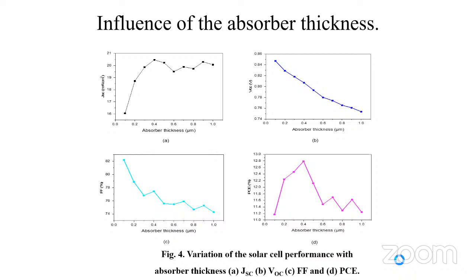JSC of 20.47 is achieved when the thickness is 400 nanometers, mostly due to the larger absorption coefficient of the perovskite. The increased recombination of free charge carriers in the thicker absorber layer may be responsible for the steady drop in VOC. The higher series resistance could explain the decreased value of fill factor with regard to absorber thickness. Furthermore, PSC power conversion efficiency rises first and peaks at 12.79% at 400 nanometers and then falls as absorber thickness rises. When the absorber thickness is less than the charge carrier diffusion length, the majority of charge carriers reach the electrode, increasing the power conversion efficiency. But for a thick absorber layer, recombination occurs and therefore power conversion efficiency falls as the thickness increases.